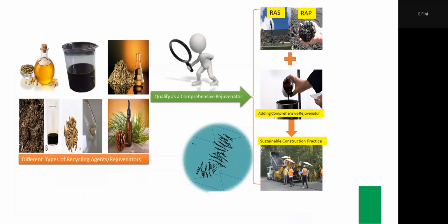on the aged asphalt. In another scenario, we add it to the virgin binder when we mix it with the asphalt in the tank. Either way, or the line that adds the other modifiers could also add the rejuvenator. When the rejuvenator finally gets into your mixture, it's supposed to restore some of the properties that I showed you. Because we always think about aged material being more prone to crack, one thing we always try to achieve with rejuvenator is crack resistance.